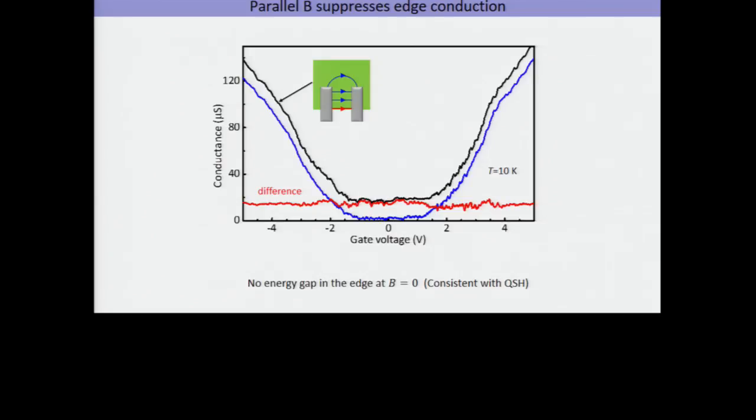So what you see is the conduction, this blue trace is just the same as the black trace, but displaced downwards because you switched off the edge conduction. And the difference between them is this red trace here. It's very uniform, you see. So we know that at least in this range in the middle here, this red trace corresponds to edge conduction. So it seems a reasonable hypothesis that this is edge conduction that is continuing to occur even once the bulk is turned on.